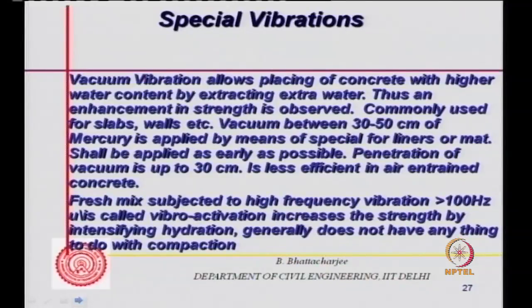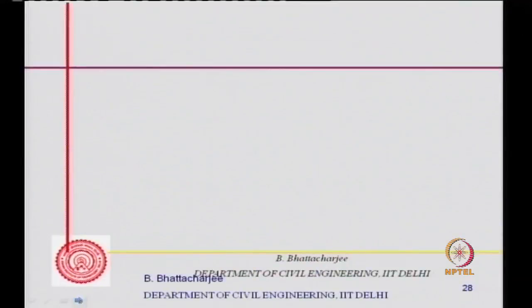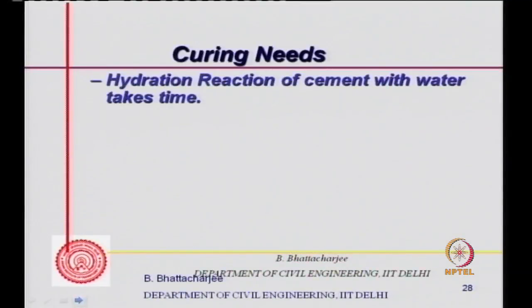A fresh mix subjected to high frequency vibration over 100 hertz is called vibro activation. It increases the strength by intensifying hydration, and generally does not have anything to do with compaction. So if you have used high frequency vibration, then the hydration process increases, nothing to do with the compaction. Right, so these are special cases. Now let's look into the second part of our discussion, that is curing.